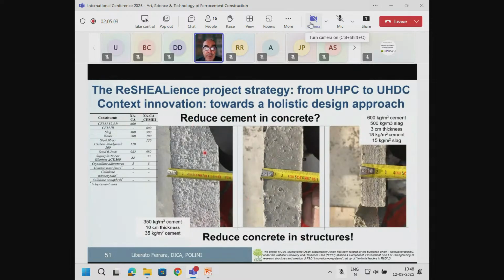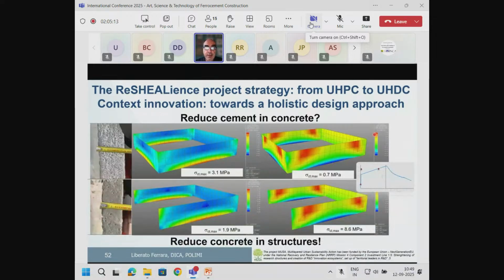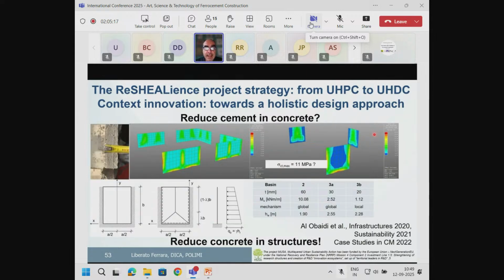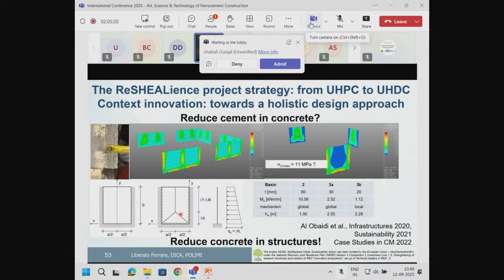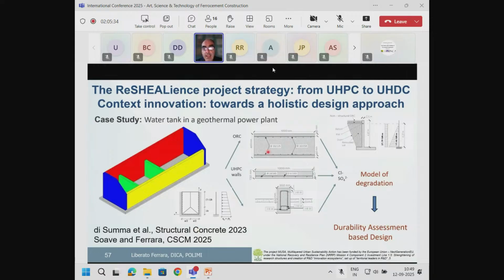and with the great saving of material, because for square meter of tank wall, we went from 80 to 35 kilos of cement, so great savings. Obviously, you need to develop reliable structural analysis, structural design. For the slabs, we designed with the yield line methodology. These materials require some nonlinear design, but it's okay. And also we validated this concept with real full-scale tests, and we were able to save in the real structure, to save great amount of material.